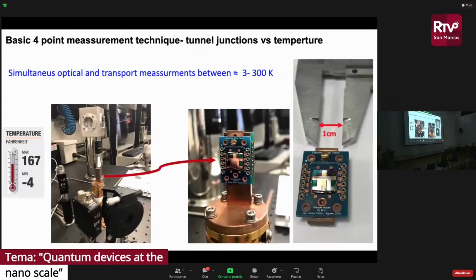We do the measurements in this system that works at temperatures between 3 and 300 K approximately. And the important thing of this system is that I can do not only transport measurements, but also optical measurements. So if you have samples which you would like to measure optically and by transport at the same time, we can do it here.